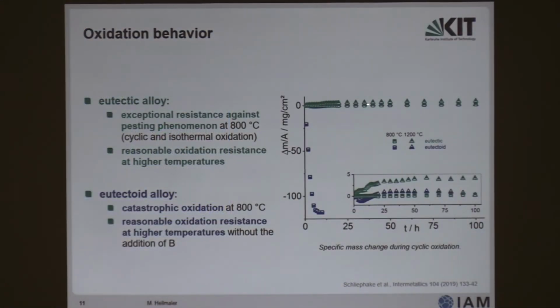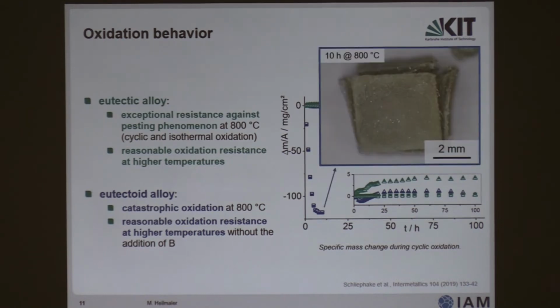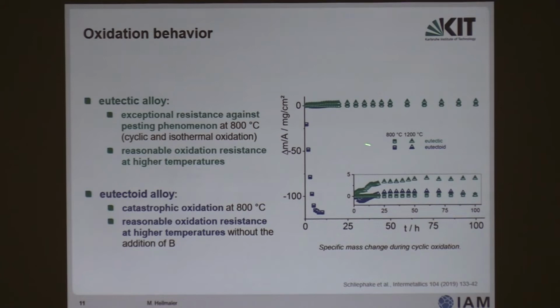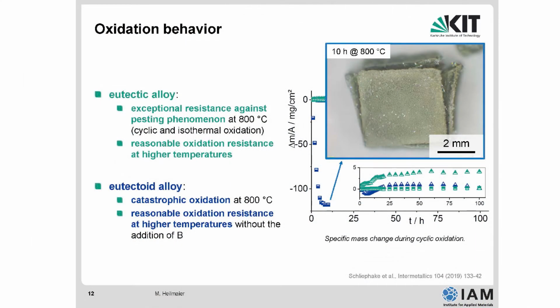It's actually underneath the other two, the eutectic alloy at 800 and 1200 degrees C. Basically what you see here, after 100 hours, not much has changed for the two temperatures of interest, and also for intermediate temperatures. But what you see is for the eutectoid alloy, this one here, the squared, half-filled square symbols, this goes down rapidly, ending up down here with a dramatic weight loss.